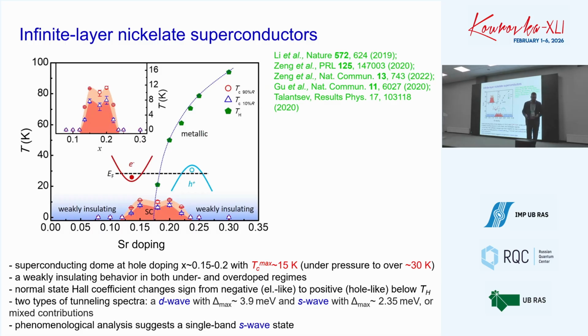I mean, this is a hint that upon doping in this system there is a crossover in transport properties. Some smoking gun, or Lifshitz transition, that the electronic structure changes upon doping, and possibly magnetic fluctuations or tendencies to competing magnetic states that also change upon doping. Well, this is a summary of many experimental results.